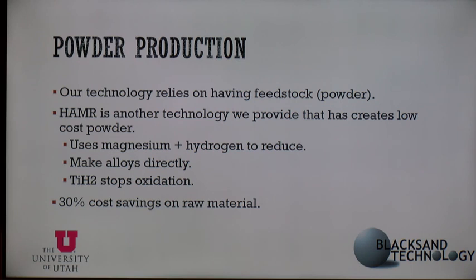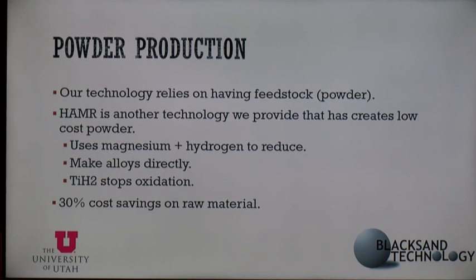Previously, the most common process, I'm sure you have heard of the Kroll process, uses TiCl4, which is a very harmful substance that can be corrosive. We eliminated that and started with titanium oxide, which is very safe, we consume it in toothpaste. It's everywhere around us. It's very safe and economically feasible. It creates titanium hydride, which is basically hydrogen with the titanium to stop the oxidation. So to keep oxygen levels low, we use titanium hydride. This can result in about a 30% cost savings on raw material. So that's just our baseline for raw material.